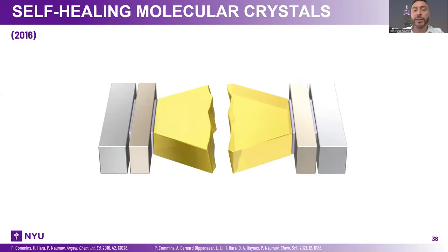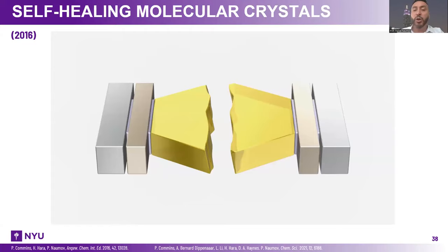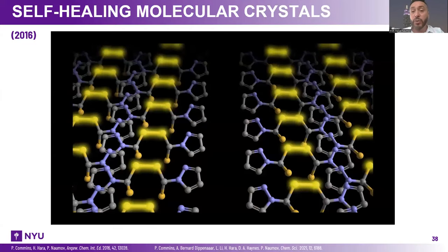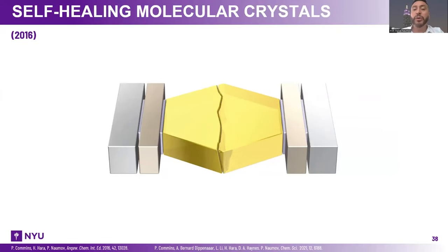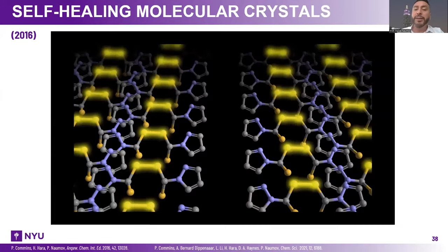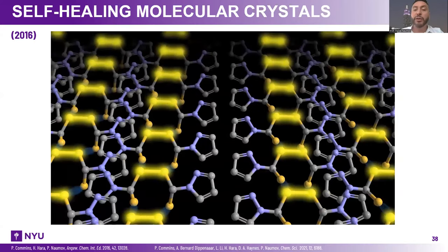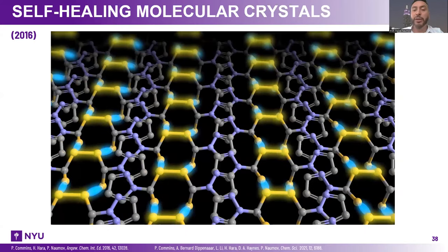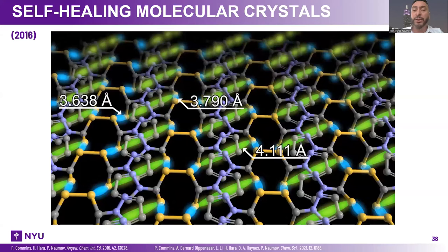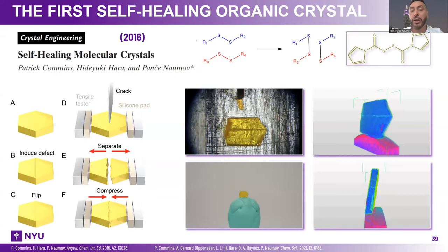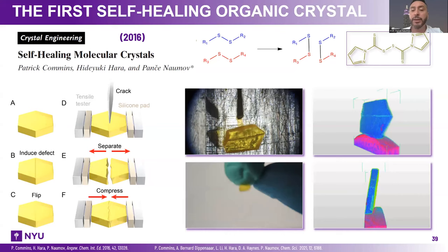And indeed, in 2016, we tried to find a dynamic covalent chemistry, and we decided to go with the disulfide bonds because they are very common and perhaps the most commonly used dynamic covalent bonds, where basically we use dynamic covalent chemistry to self-heal the crystal by putting the two pieces together. And of course, there have to be structural prerequisites for this to happen, but it works. Unfortunately, it works to a very small extent, 5 to 6% efficiency in the healing. Nevertheless, we have visual and also analytical evidence that the self-healing has occurred.